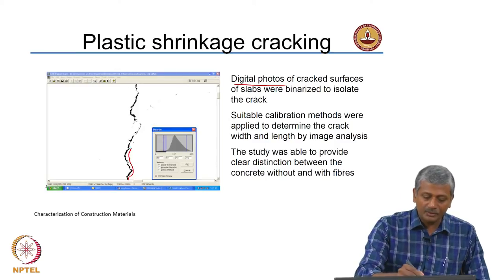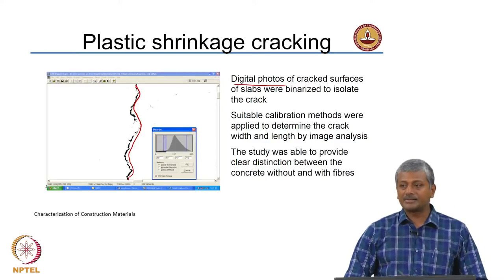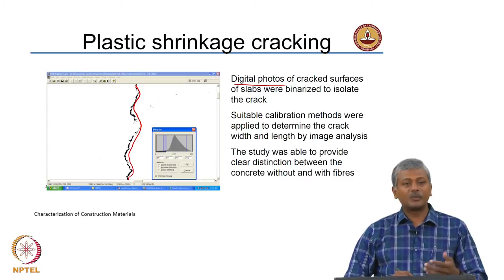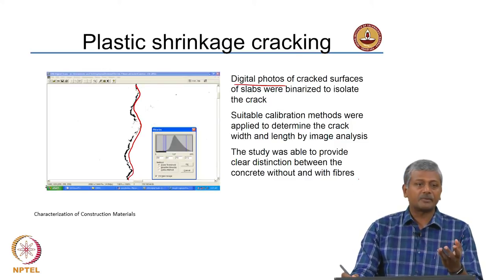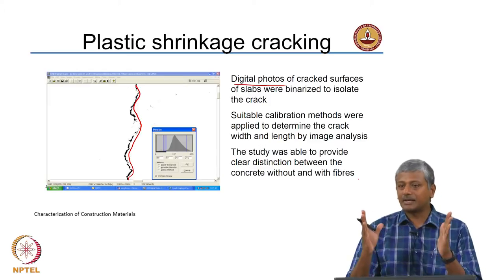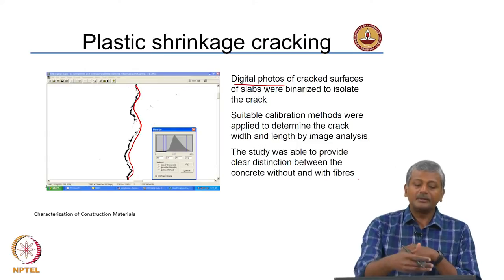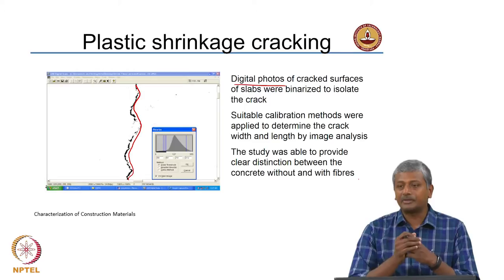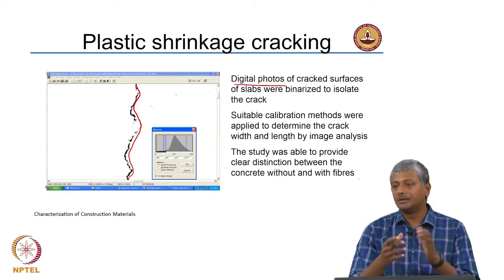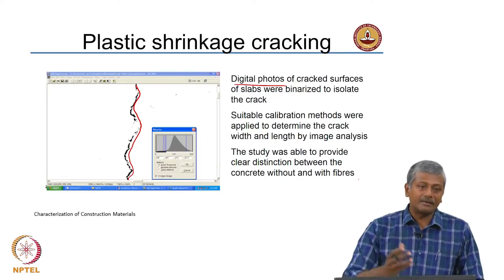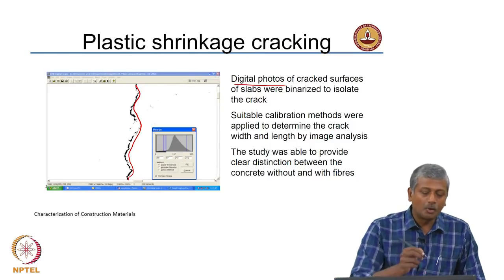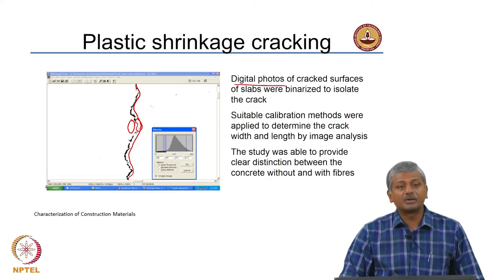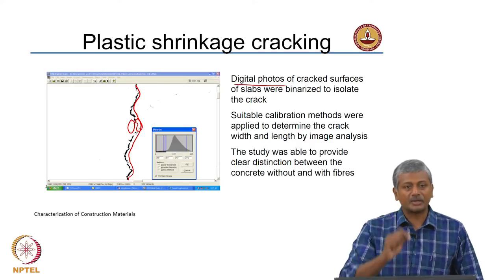You can trace the length quite easily using a polyline tool, but what is more critical here is that we also wanted to look at the crack width. Crack width was determined by a crack width microscope, which is used to look at how cracks get wider as loading increases. This was used to determine the overall cracking area. You can determine the width at different locations, calculate an average crack width, and convert the entire thing into an area. If the crack width is not clearly observed in the digital photograph, you may have to image it using a crack width microscope for much better magnification.